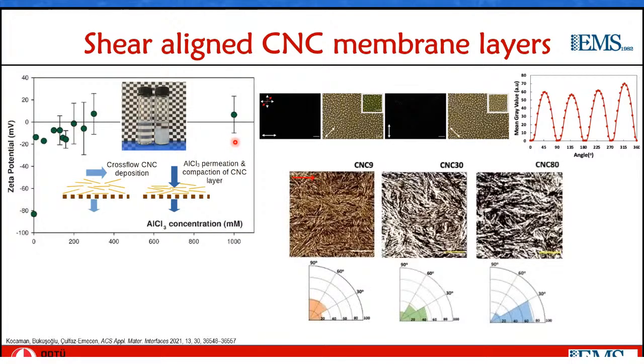The alignment is also visible in atomic force microscopy images. Here you see the flow direction, and 9, 30, and 80 are the flow rates. At 9 milliliters per minute, we see no preferential orientation of the nanocrystals. With 30 milliliters per minute, we start seeing a little bit of preference towards the flow direction, and with the highest shear, they're mostly aligned in the flow direction.